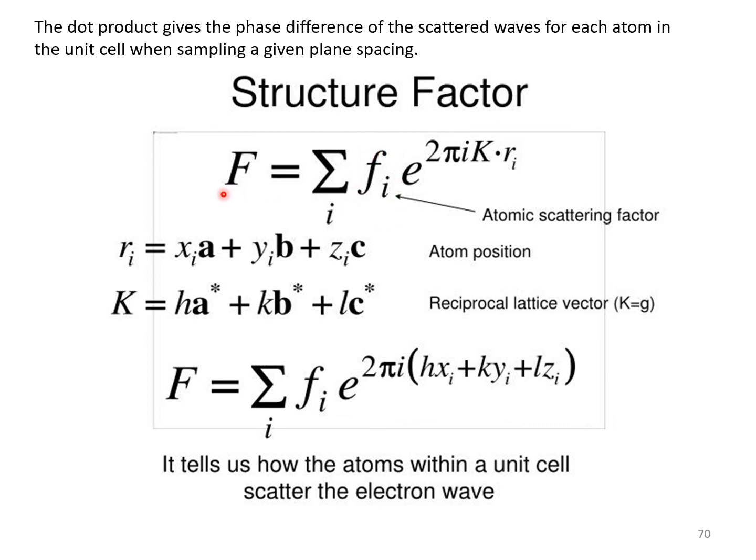And the intensity of scattering for a given plane, for a given arrangement of atoms within a unit cell, is given by this expression. I'll talk about the derivation of this expression in lecture 2. But basically, if we have a plane HKL and atomic positions xi, yi, and zi for each, and we sum up all of these intensity variations, we get a strength of diffraction, which is the structure factor. It's very important in terms of characterization.